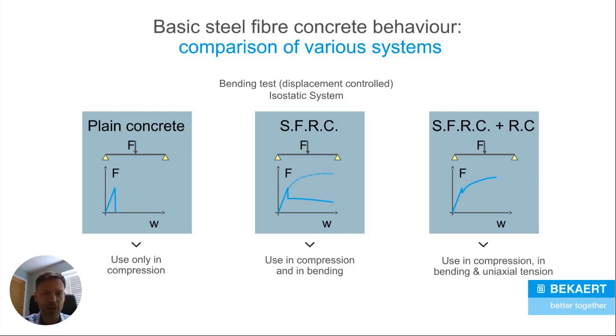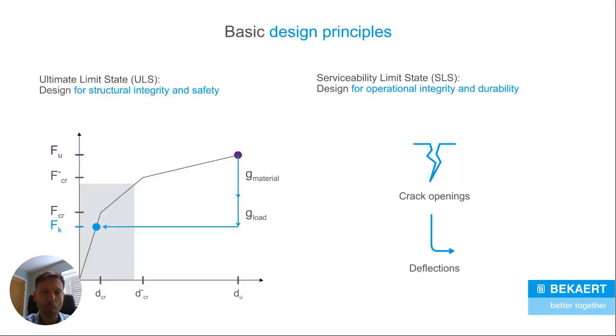If you add fibres to this concrete, SFRC is steel fibre reinforced concrete, what will happen is you will not increase the first crack strength of that sample, but you will give it post-crack toughness. So what happens is the fibres will not increase the strength of the concrete until there is a yield, but then it will stop that sample from failing. If you have fibre concrete and some traditional bar in there as well, what you will get is effectively a bending hardening situation, which is something important to remember in a few slides' time.